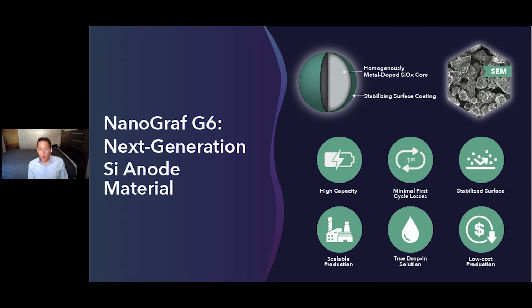And I think the way we try to differentiate the technology is that we are a true drop-in solution. This can be blended with graphite in a traditional slurry, coated, calendared, no changes to the manufacturing process at all. And we're doing this all with a material that we believe will achieve the same cost or lower cost as first generation silicon oxide at scale.